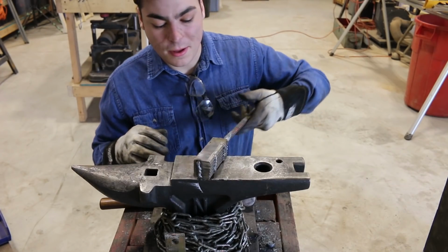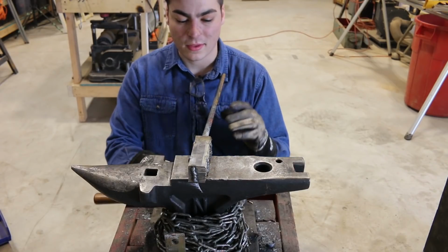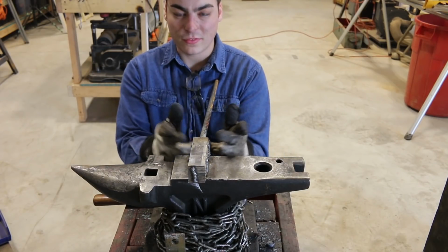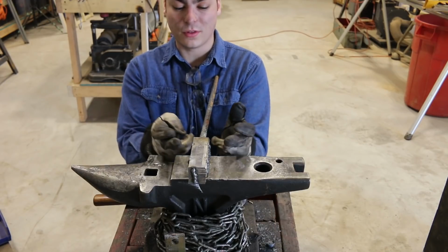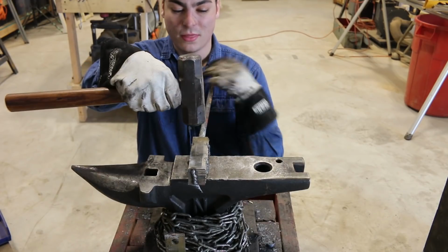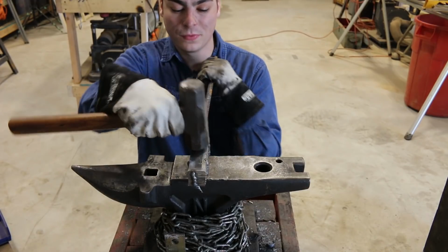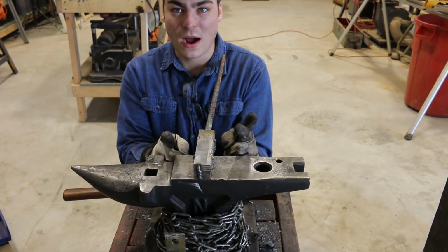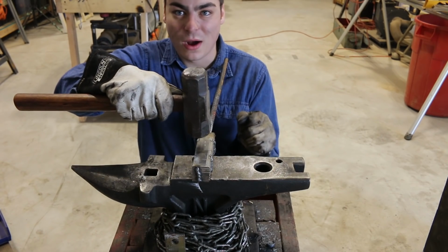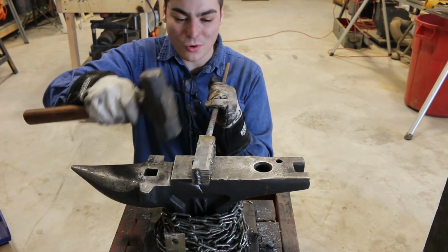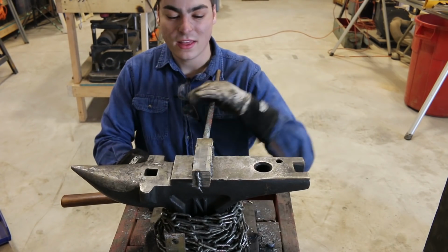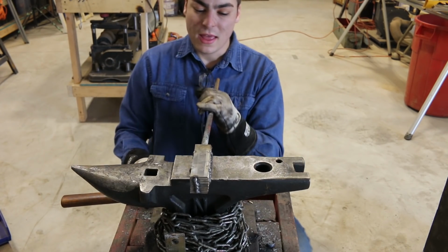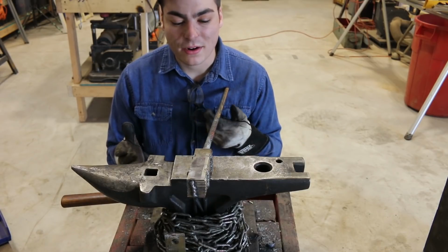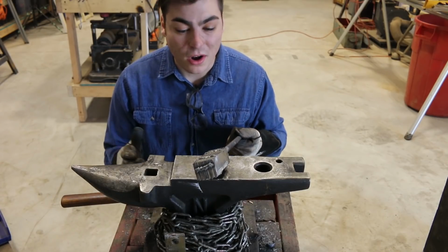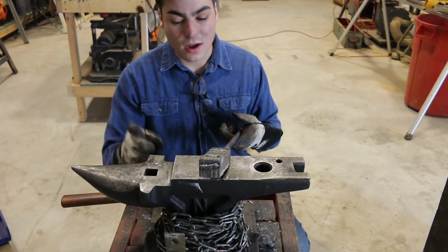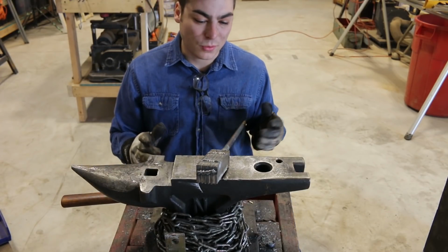All right, so helpful hint number 1 is to use a steel width that fits the width of the hammer you're using to set it. So if your billet is this wide and your hammer is only this wide, you're gonna be going back and forth in a zigzag in order to set that whole billet. And you may end up with an inconsistent pattern. You may end up with voids that actually don't forge weld at all. And that's the number one thing that I was struggling with when I first started doing Damascus.